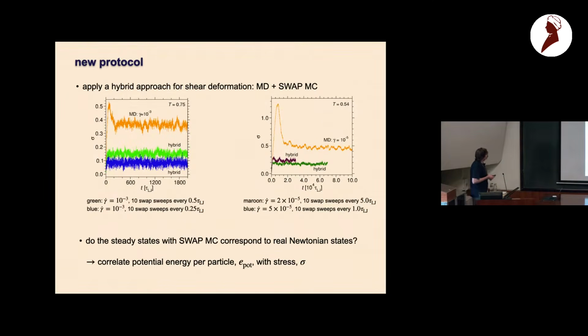Okay, and this is what we get. This is, first of all, at a temperature of 0.75. It's very large. This is via straightforward MD, and this is via the hybrid scheme, and we get states here at very low stresses.